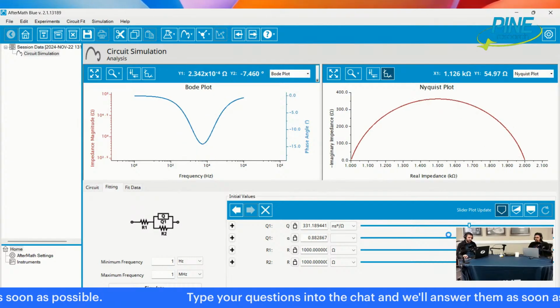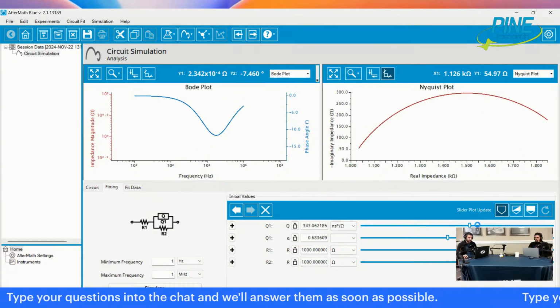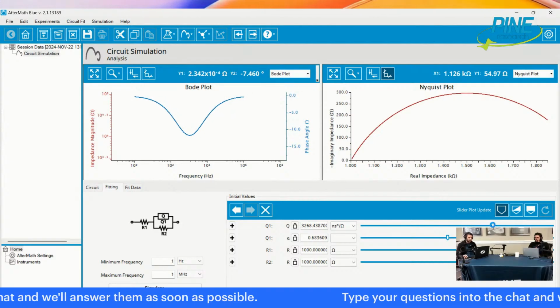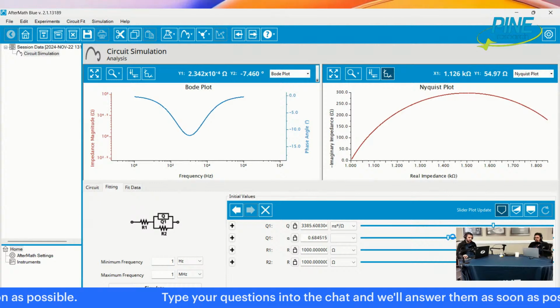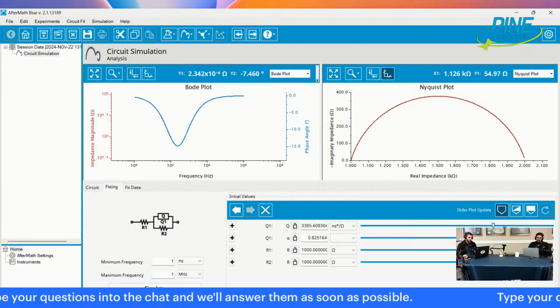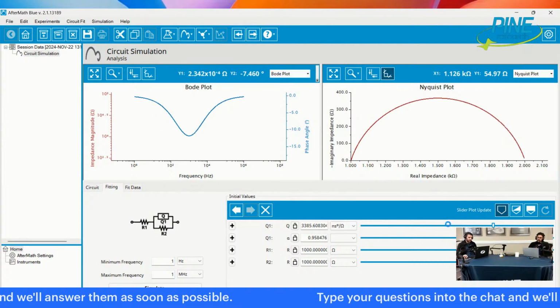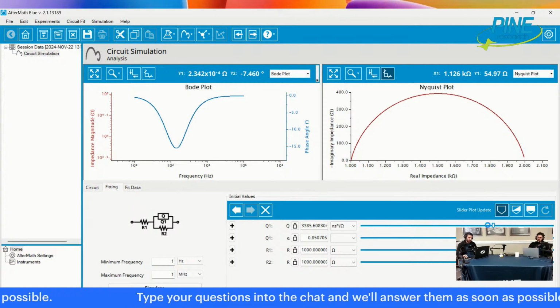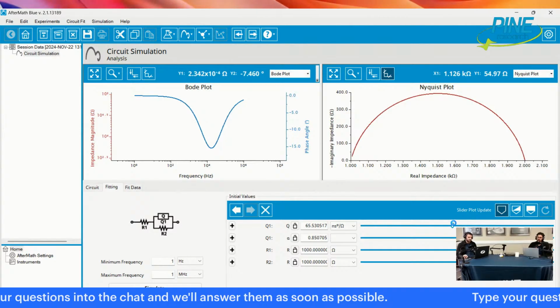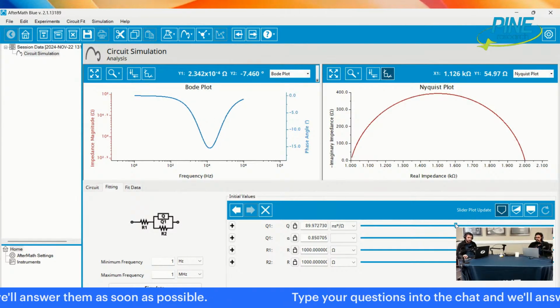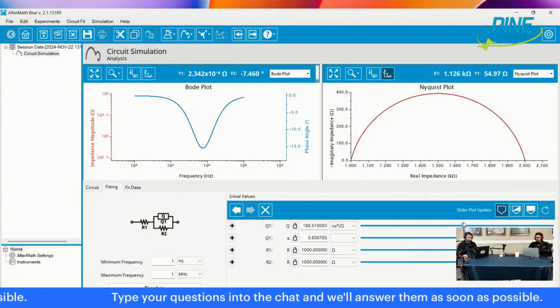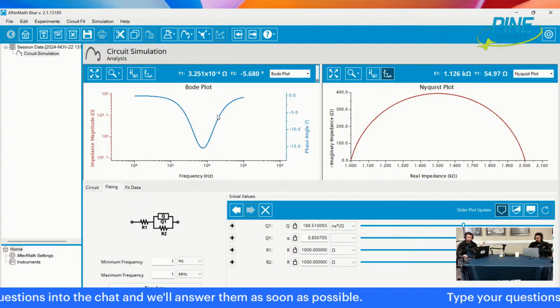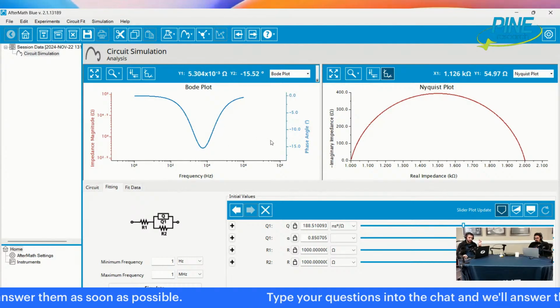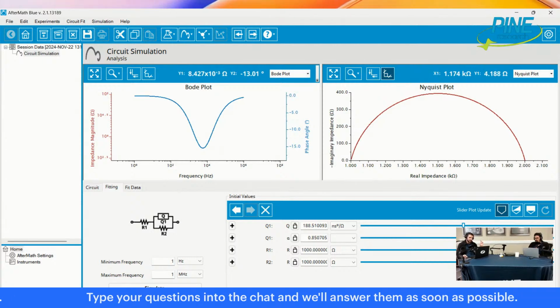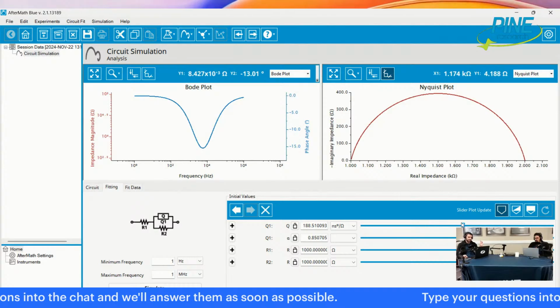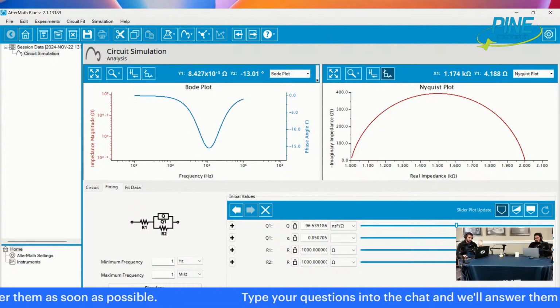So if the peak was very broad and non-ideal, for instance, when you started like this, one interpretation of it is that it became more ideal. You see how it gets a sharper peak and less broad. And also it's moving in the wrong direction. It's moving more negatively. So to counteract that, I could say the capacitance is decreasing. So in summary here, one possibility to answer your question, just practically based on the values of the components that are at play, is that the phase angle peak moving to higher frequency and becoming sharper means that it is behaving more like an ideal capacitor with a lower capacitance value. Okay, so that's just one way of looking at that.